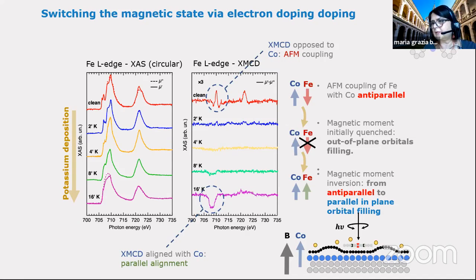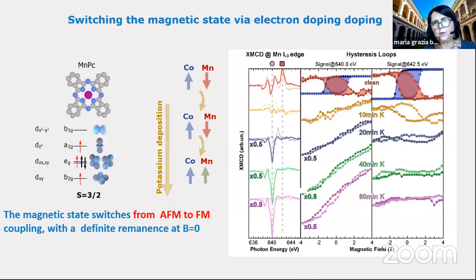We also made this experiment with other molecules. In this case it is manganese, and it was really interesting because we observed the switching, but we were also able to measure a hysteresis loop. So I can summarize these results.